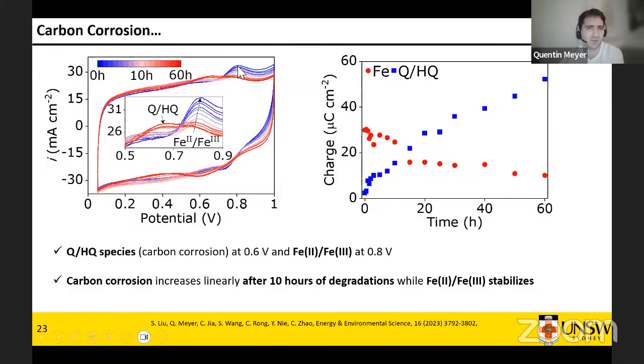So this peak around 0.8 volt is for iron oxide, iron 2+ to iron 3+, and this peak around 0.6 volt is linked with carbon corrosion. And basically, this peak becomes much smaller over time. This peak's much larger. So we've deconvoluted them, doing a bit of data fitting to try to get the peak area. So this is sort of accurate, but probably there's still room for improvement. But this is overall the picture we get.